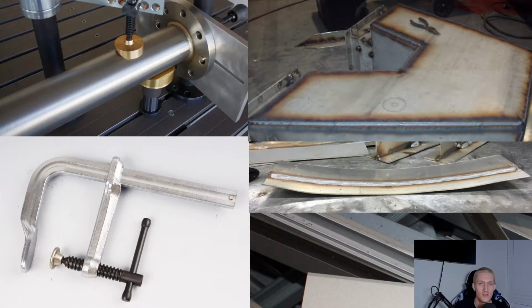Welding stainless steel has similar characteristics to carbon steel, but when welding stainless steel, it likes to trap heat and distort. You can control distortion by bracing the weld joint or spreading out your heat. You can brace the part by use of a jig or clamps, or by placing a piece of wood or a bar between two sides to help it not close in.